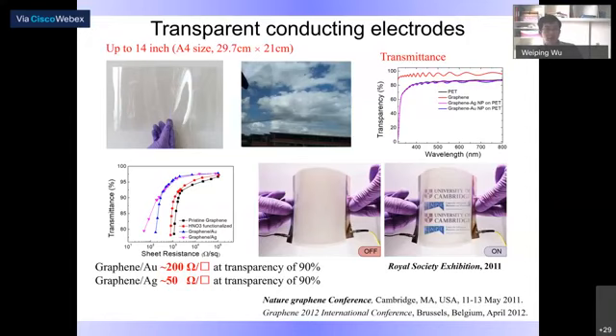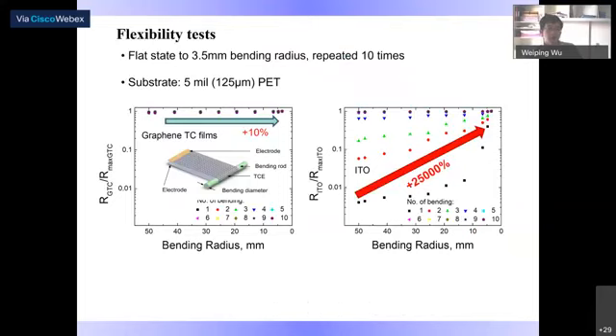By sandwiching a liquid crystal dispersed in polymer, also called PDLC, with this transparent graphene electrode, I successfully demonstrated this smart window device, which was shown at the Royal Society exhibition in 2011. Also, these flexible graphene electrodes were tested by a bending test. Compared with indium tin oxide, an inorganic transparent conductor, the graphene electrodes only increased their resistance by 10%, while ITO increased its resistance 250 times.